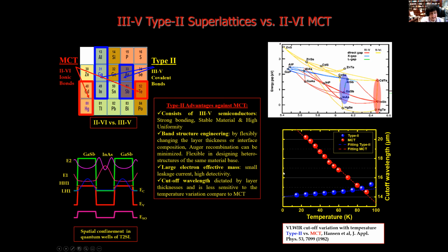So if I show you here the cutoff wavelength variation of the two detectors, one based on type-II superlattices, another based on mercury cadmium telluride, for the 14 micron. At 100 Kelvin, they are both 14 micron. When we decrease the temperature, as we can see, the wavelength of the MCT changes from 14 to 20 micron, but there is no change for the type-II. It means that the material is much more stable as a function of temperature, something that we know.